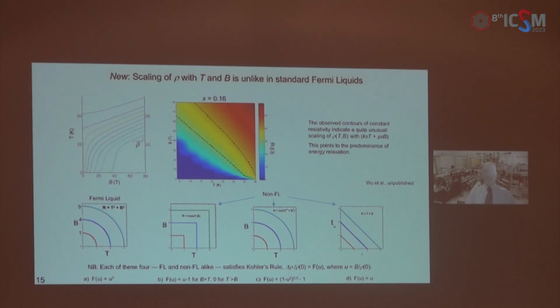Now, I want to make a couple of key points. First, every one of these, Fermi liquid and non-Fermi liquid alike, satisfies Kohler's rule, as I have shown explicitly at the very bottom. But the scaling that we see is very much unlike the Fermi liquid. And second, the linear addition is suggestive of friction in a hydrodynamic fluid due to energy dissipation on whatever excitations are there. And third, note that this doesn't follow automatically from the strange metal temperature dependence. We normally assume that the relaxation time is intrinsic, in other words, that it doesn't depend on the electric field, like in Ohm's law, or the magnetic field. But here, it seems that it does. So I would call this double strange.